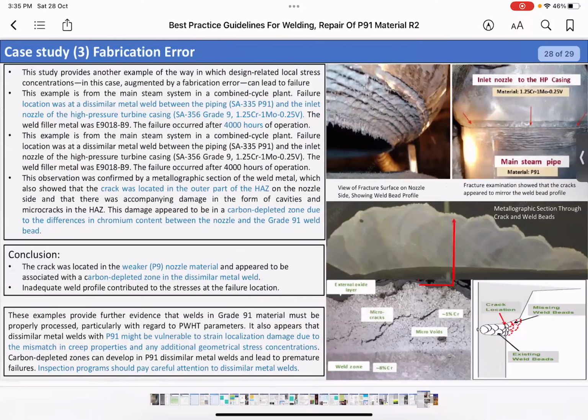The last case study is related to fabrication error. The location, as you see here, is at the edge of the weld, pipe welded to a nozzle. The nozzle is P11 material, and the main steam pipe is P91 material. The crack was in between the weld and the nozzle. The location was at the dissimilar weld metal between the piping and the inlet nozzle, the P11 or grade 9 material.